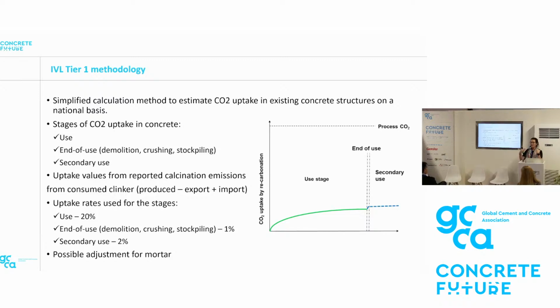And then if you move to a tier 2 methodology, you need more data, because you need to substantiate more your claims for emissions or removals. And then you can even go down to a tier 3 methodology. So we now have this 3-tier methodology that has been developed and tested against all the research that was available, and even the tier 1 accounts for the use phase. The end use phase is the secondary use phase, and the use phase, as shown, is 20%.